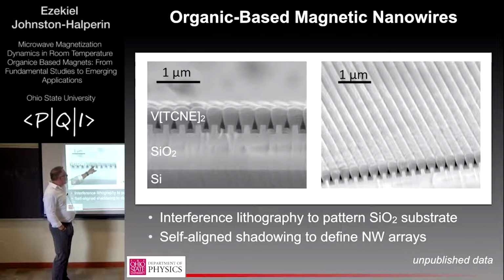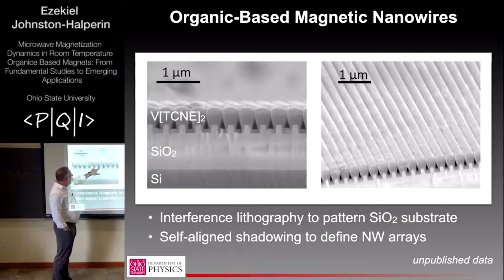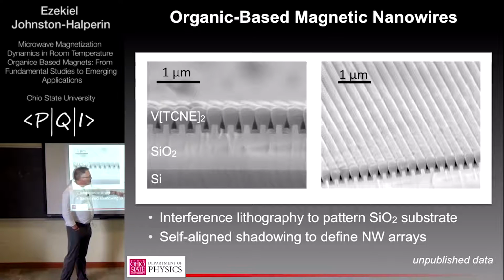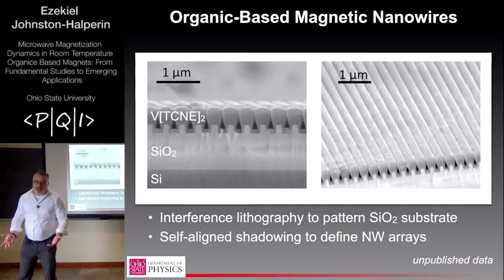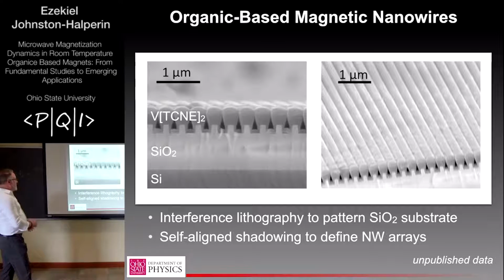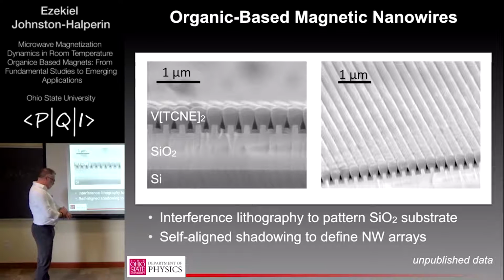So what you see is some sort of ripening happening. It's not totally obvious from this picture, but from some diagnostic growths, it starts at the corners, that it deposits faster than on the edges, and then as these corners grow out, they start to shadow the trenches, and so then you're just depositing on top of the platform, and you end up, as you can see in these two different perspectives, with arrays of nanowires. And so that was very cool,